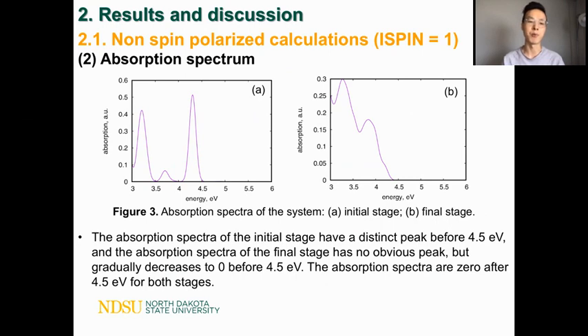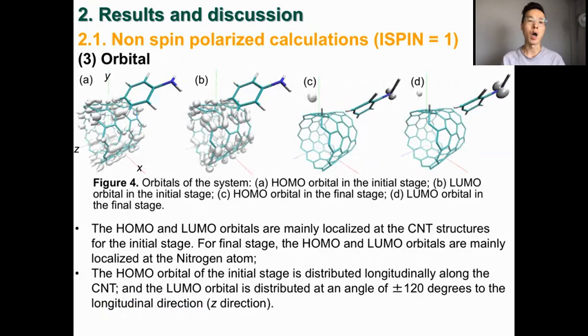I also studied the absorption spectrum of the system at two different stages. As you can see from the figure, the absorption spectrum of the initial stage has a distinct peak before 4.5 electron volts. And the absorption spectrum of the final stage has no obvious peak, but just gradually decreases to zero before 4.5 electron volts. And the absorption spectra are zero after 4.5 electron volts for both stages. So next, please.